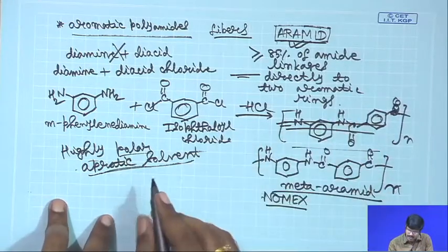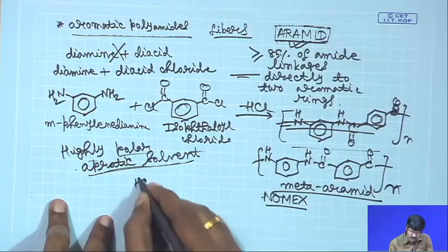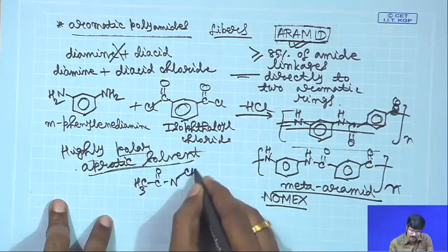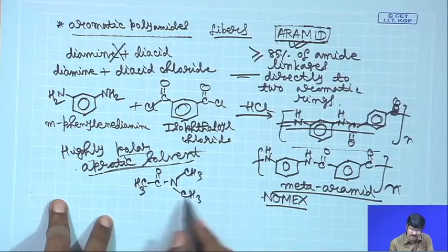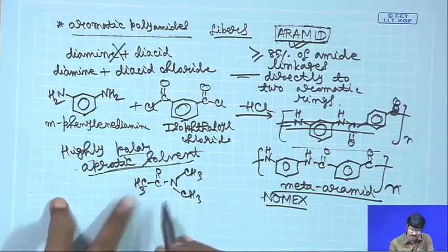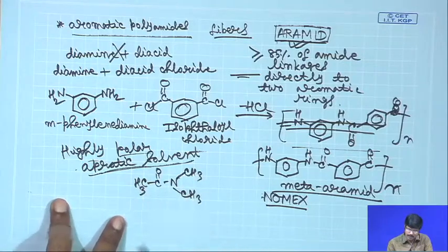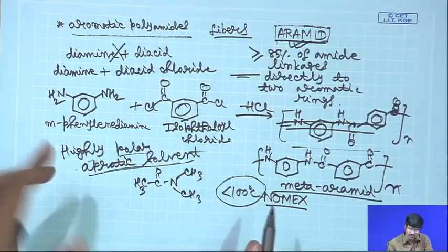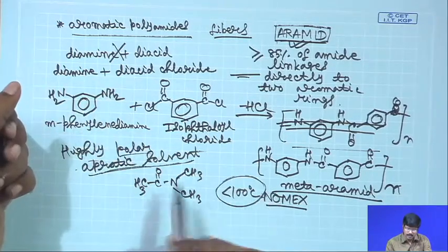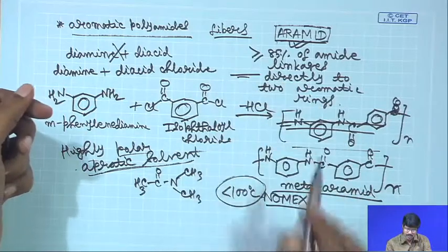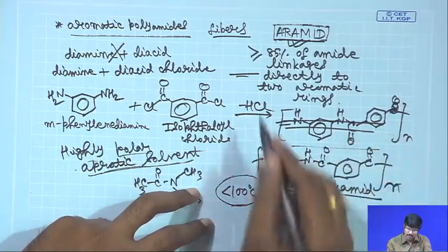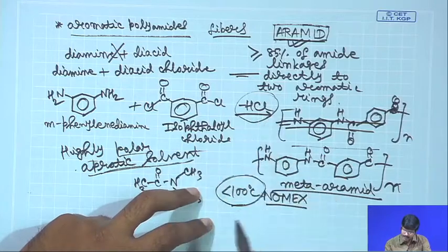So, in this case what you use is dimethyl acetamide. So, this is acetamide, CH3CO NH2. So, instead of 2 hydrogens, if you have 2 CH3 units, it is dimethyl acetamide. This is a polar solvent, but this cannot donate protons. So, polar aprotic solvent. Temperatures are typically less than 100 degrees Celsius. Compare that with the temperatures that we use for your aliphatic polyamide preparation, upwards of 200 degrees Celsius there, and here because this is activated, you do not need very high temperature, and you typically use a base in order to scavenge the liberated HCl, the acid,